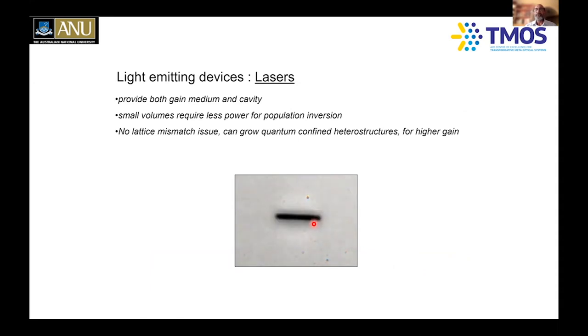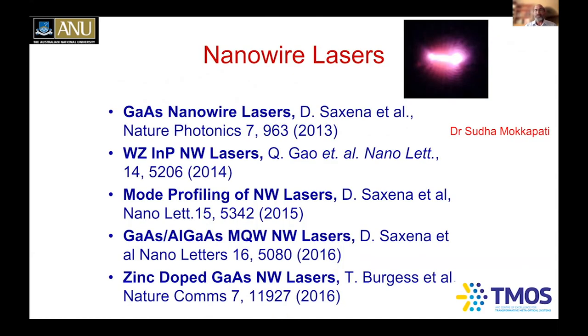Both ends of the nanowire act like mirrors because of the refractive index contrast between the nanowire and the surrounding medium. So if you design the nanowires correctly and grow good quality nanowires, each nanowire in principle should act like a laser. That's our aim, and we're able to make these nanowire lasers. Of course, we've been working in this area for a long time, and we demonstrated a wide variety of nanowire lasers.